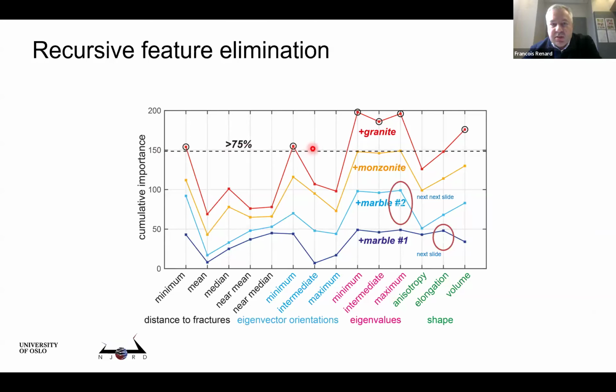What we see are the features that are important. This one, the one with the black circle, is the minimum distance to fracture. So if a fracture is close to another one, it will tend to grow more. That's also the orientation of the fracture. If a fracture is vertical, it will tend to grow more than if it is horizontal.